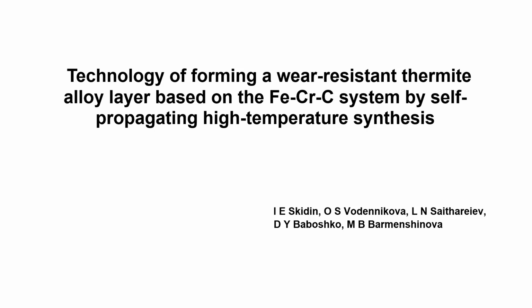To your attention, the results of the research work: technology of forming wear-resistant thermite layers based on the ferrum-chromium-carbon system by self-propagating high-temperature synthesis. It is known that it is optimal to pour molten metal into a mold at a temperature close to the crystallization temperature. But even so, it is not possible to obtain two-layer bimetallic castings due to the lack of a quality zone for the formation of functional layers.